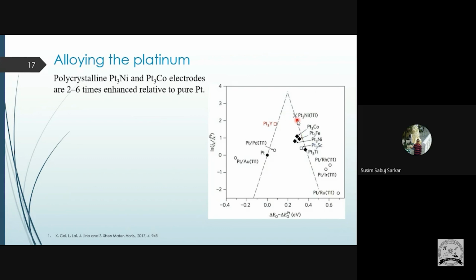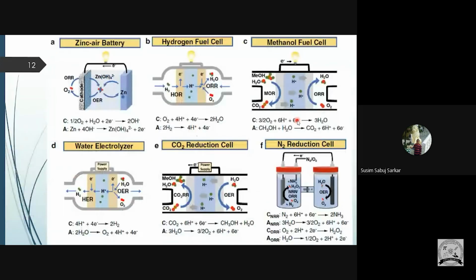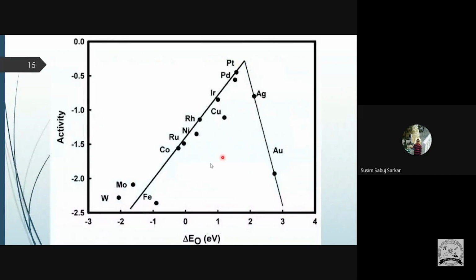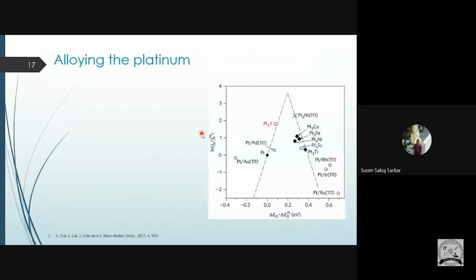If you remember the graph, you can see that nickel, though it has very low activity, its oxygen adsorption energy is very low. So in that case we can combine nickel with platinum, or also cobalt with platinum, because these are cheaper. But ruthenium and iridium are not very available, so we are not combining ruthenium or iridium. We are mainly targeting other non-precious metals like cobalt or nickel.